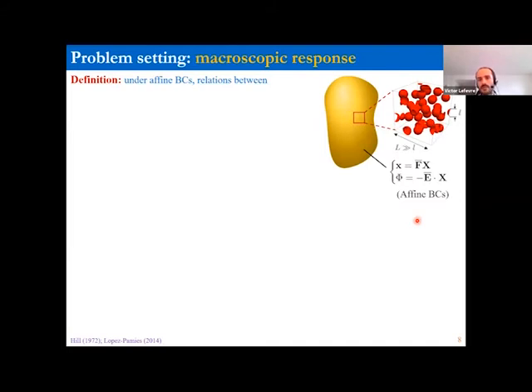And these boundary conditions represent essentially what people want to do in an experiment when they're trying to extract material behavior. And this is because when you apply these boundary conditions, the deformation and the polarization in the specimen are uniform, and this irrespectively of the geometry of the specimen. So what you're going to measure on the boundary of the domain is going to be the same everywhere you measure it. And then you can relate what you measure and obtain the considered behavior for the material. So that's what we want to do here.